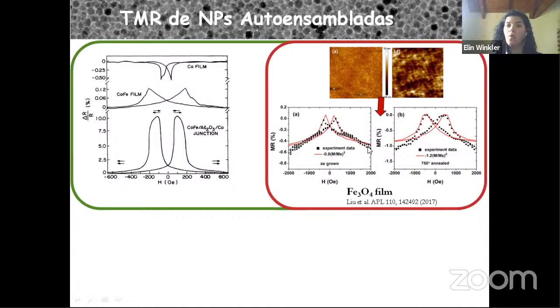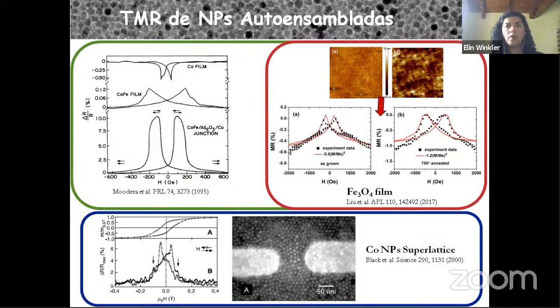The resistance is low when the magnetization of the system is ordered, and is large when the system is disordered. This maximum is related with the coercivity field of the system. Tunnel magnetoresistance was also observed in devices formed by metallic nanoparticles. This image, for example, corresponds to cobalt nanoparticles that are deposited, and it measures the conduction through these two electrodes. So again, the system presents two resistance states.